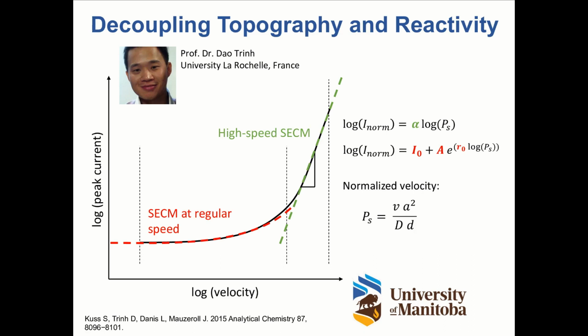So in this graph, the curve represents our experimental data. If you're able to scan at high scan speed SECM, we are looking at the region of the graph that is linear. The function in this case that is fitted to the experimental data is shown here on the top in green, and depends on the slope of the curve mainly.